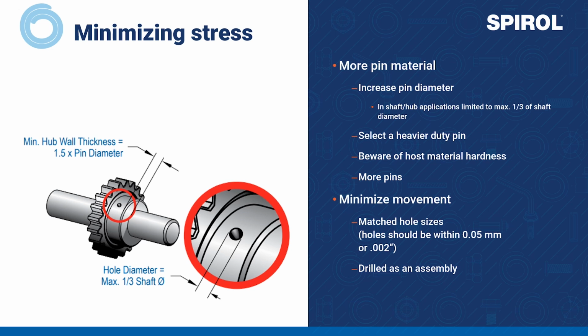After that, we can take a look at increasing the amount of pin material. More material means a larger cross-sectional area of the pin and therefore less stress. We can either increase the pin diameter itself while still staying within the geometrical constraints of the application, which, for example, in a shaft and hub assembly, the pin diameter should not exceed a third of the shaft diameter. Another option is to move to a heavier duty pin.